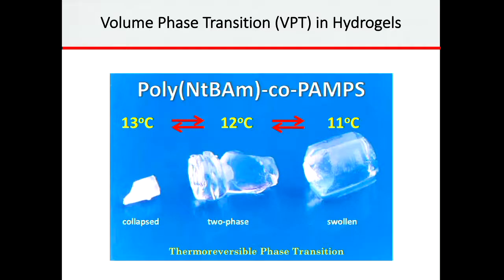And what is very special was, of course, that these gels show volume phase transitions. For example, you can see the two equilibrium states. On your left-hand side, you will see the collapsed state. On your extreme right, you will see the swollen state. And in between, you will see a state where the two states coexist in equilibrium. And just a 1 degree switch of temperature, basically, can change the swelling. All right? So if 12 degrees is the volume phase transition, at 11 degrees it is fully swollen, and at 13 degrees it totally collapses. Okay? So this is the feature that we had.